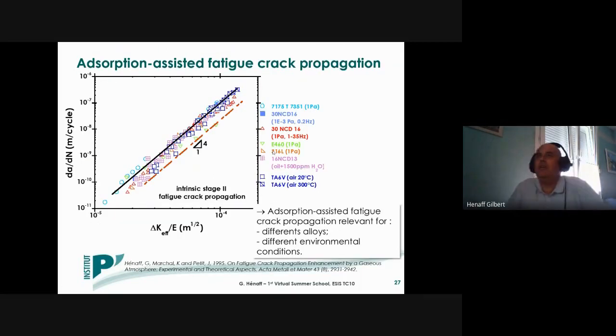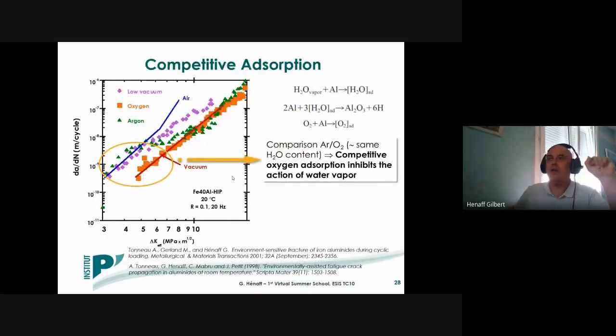And we also collected different data on different alloys for different environmental conditions, generally low water vapor pressure conditions. And again, we observed that we have quite a unique relationship, which is characterized by the same fatigue crack growth rate enhancement factor, but again with the same fourth power law dependency, which is the reason why in the basic fatigue crack growth equation, we did not change the exponent and only the coefficient. So I think I'm running out of time, so maybe I do not have time to detail this.